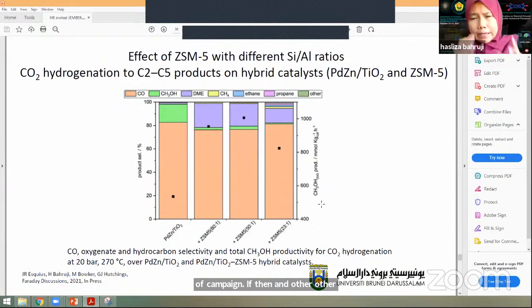This gives an indication there is a possibility for us to actually convert our CO2 directly into fuel, which is olefin or paraffin mixtures. This is basically a hydrocarbon that is going to be beneficial for fuels. And then when we vary the reaction temperature by using this hybrid catalyst, palladium zinc oxide with ZSM5 with silica to alumina ratio 23, what we see here, DME is starting to favor the reaction at low temperature.